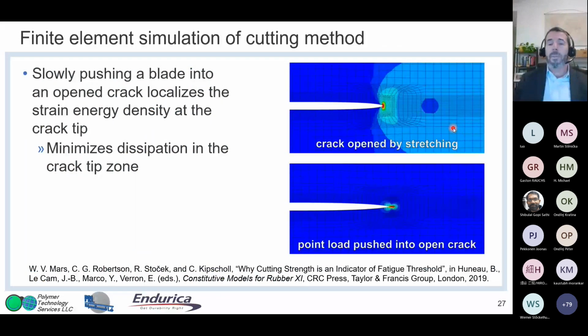And the whole goal of the blade is to localize the strain energy density. If you just open the crack from the far field, as I mentioned earlier, a lot of that strain energy density doesn't make it to the crack tip because of dissipation. But when you push a blade into the tip, it localizes the strain energy density to minimize dissipation. And that was shown with a very basic finite element simulation.